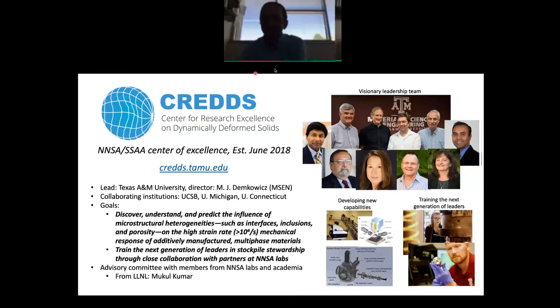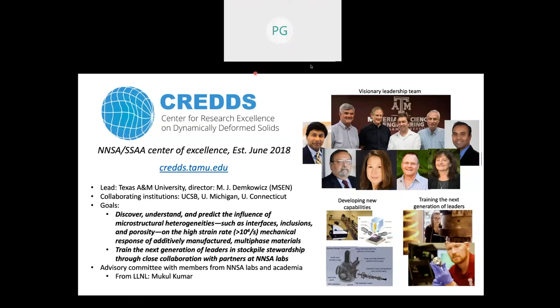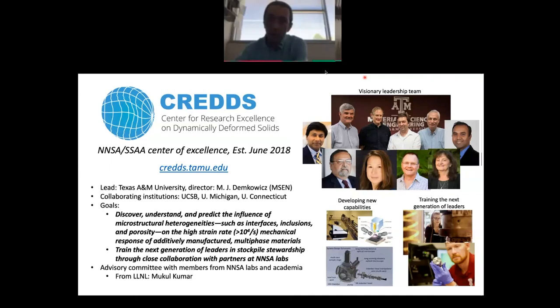So Arthur Tam asks, how does electronic heat conduction affect the cooling of the thermal spike, especially in regard to compactness? Yeah, so absolutely, the molecular dynamics simulations that I've been showing you do not take into account the electronic contribution to thermal conductivity. And I would say that that is probably the largest source of uncertainty in those calculations. So with electronic conductivity, I expect that the thermal spikes would cool faster.